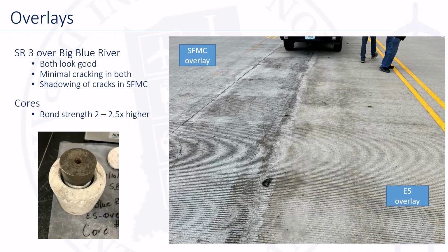This is another project, State Road 3. This is one of our earlier overlays. We actually had some cracking on both of these, but you can see on the silica fume on the left, the shadowing of the cracks. This is after a rainfall where the water is getting down into the cracks, whereas the E5, the cracks were so tight and we didn't have any of the water or moisture getting down into that deck.